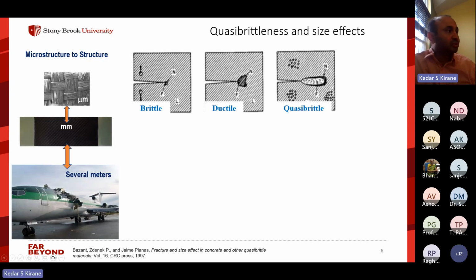So, understanding this process, this is called the fracture process zone, as I'm sure you all know. The process zone size is usually more or less a constant. So depending on the length scale that we are operating at, the role played by the process zone increases or decreases in importance. So for instance, for very small scales, probably everything is the process zone. So then it is extremely important. And for very, very large sizes, the process zone is negligible. So then the behavior can be classified as actually brittle.